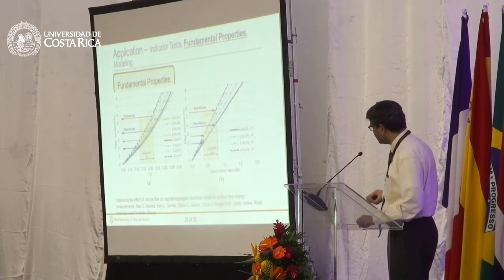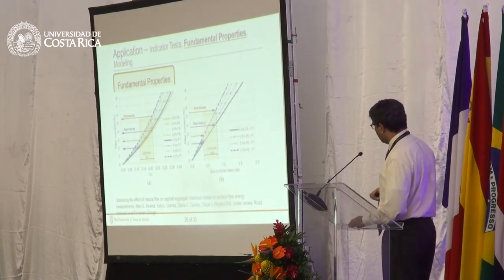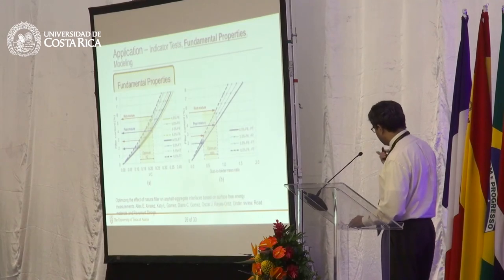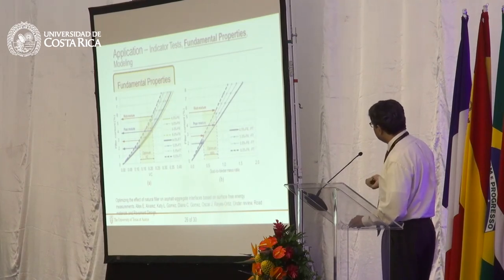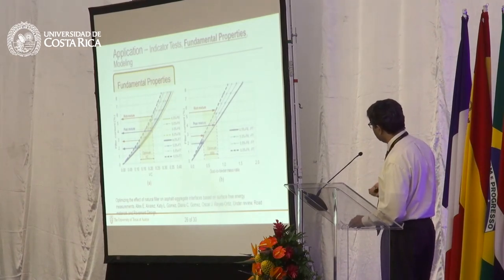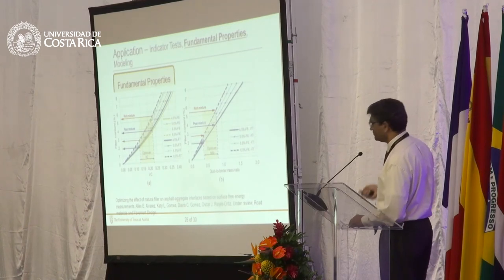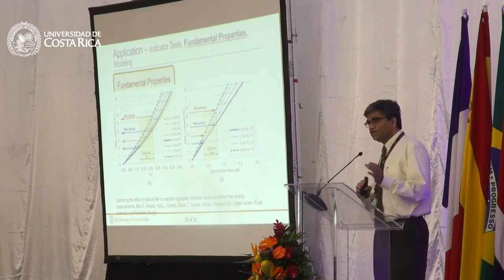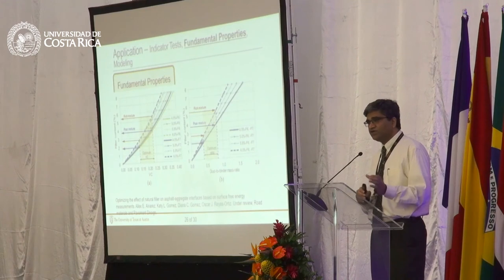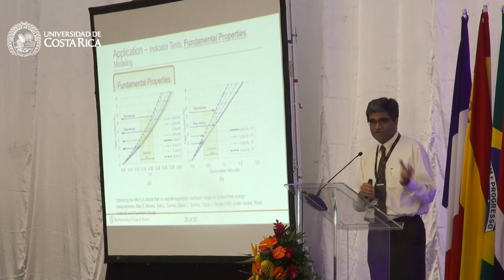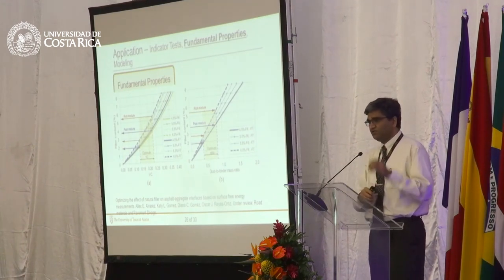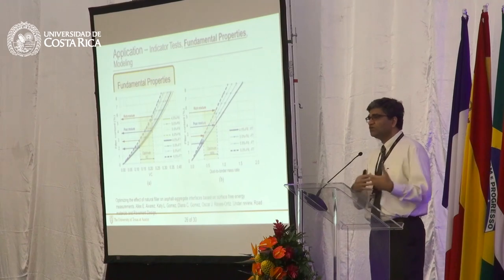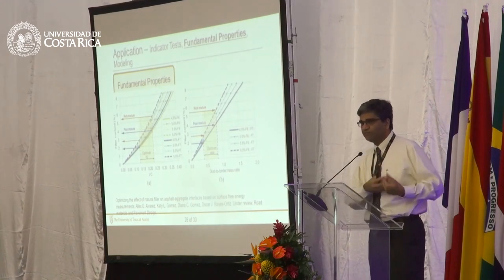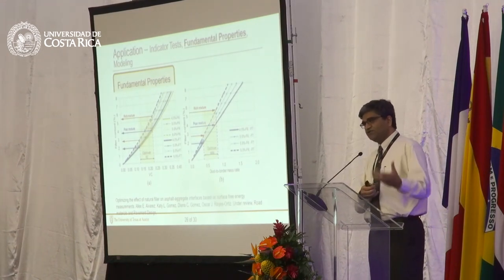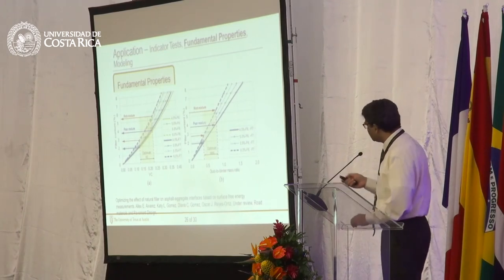Here's another example from another colleague and friend of mine, Dr. Alvarez from Colombia. He just finished this study and he was kind enough to share the results with me. What he did was he looked at the volumetric ratio of fine aggregates in different mastics. So he changed the volumetric ratio of fines in mastics and measured what the surface energy of the bulk of that mastic was based on these changes. And what he found was there was really an optimum.